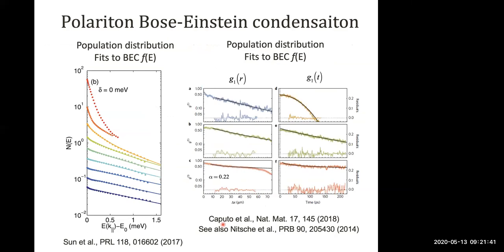So this kind of equilibrium physics has only recently been observed in inorganic microcavities and only in the best microcavity platforms available, which are those fabricated in the group of Loren Pfeiffer at Princeton, using those systems which have Polariton lifetimes of several hundred picoseconds, so much longer than the thermalization time in the system. David Snoke and Keith Nelson showed that if you look at the occupancy of the Polaritonic states as you increase the Polariton density, you can get a near perfect fit to a Bose-Einstein distribution where the only parameter which is changing is the chemical potential.